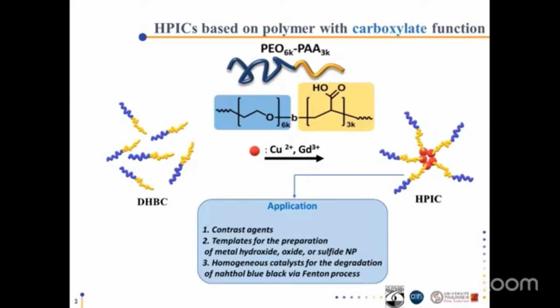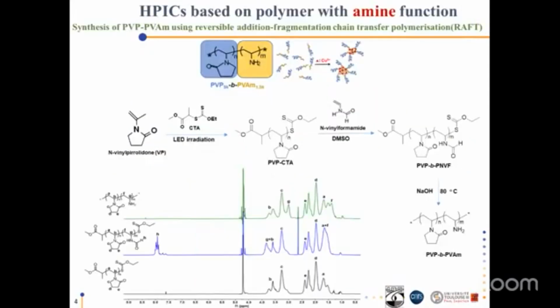There was reported the formation of stable hybrid colloidal suspensions when mixing multivalent metal cations with double hydrophilic block polymers containing a polycarboxylic acid block or polyphosphonic acid block. Such systems have been employed as highly efficient contrast agents or templates for the preparation of metal hydroxide, oxide, or sulfide nanoparticles. HPICs loaded with copper or iron have also been successfully used as homogeneous catalysts for the degradation of naphthol blue black via a photo-Fenton-like process.